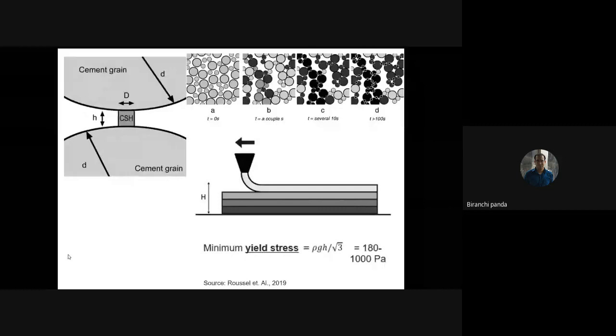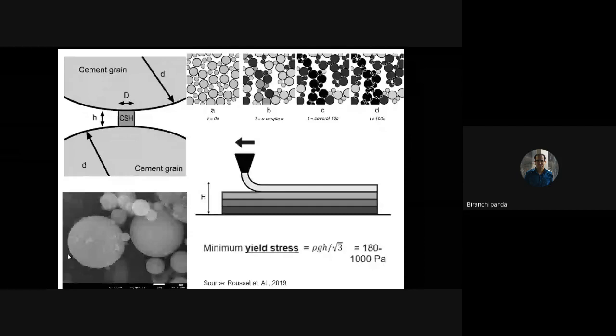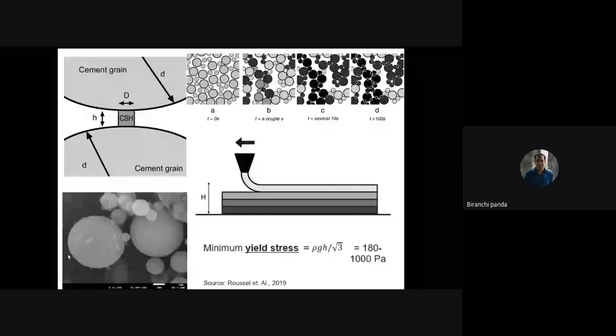But our goal was to create a more sustainable mix design. So when we wanted to create a more sustainable mix design, we tried to identify what waste materials are available near us. Then we came to know that we have a power plant that produces fly ash, and when we look at the fly ash under a microscope, it looks like a spherical ball. And then we try to replace this cement, because as you know, cement production is an energy intensive process and it emits a lot of CO2 to the environment, which is not good because it is causing greenhouse emission. So we wanted to replace the cement partially with the fly ash because it is an industrial waste, and we also wanted to create a more sustainable mix design.